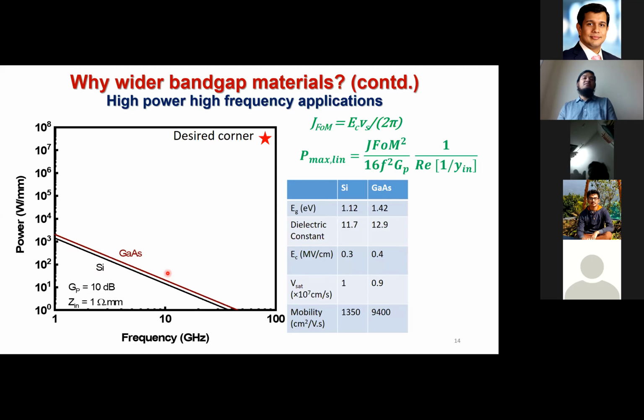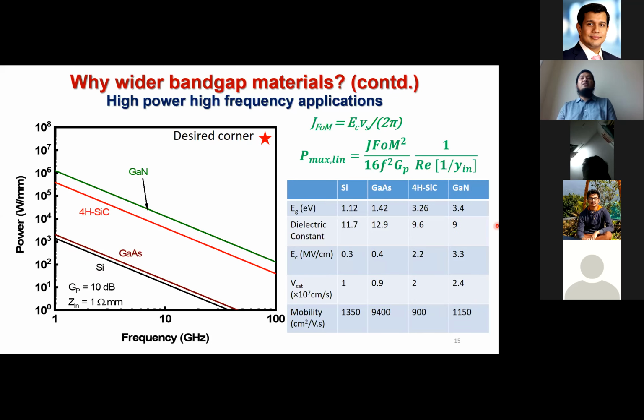Now, if you are to replace this transistor with a wider bandgap semiconductor, again, I'm talking about silicon carbide and gallium nitride, we can see that we can again get orders of magnitude improvement in how much power it can deliver in a power amplifier at a given frequency, or at a given power, how much higher frequency it can operate. Looking at this figure of merit, just from a material perspective, we are excited that if we can replace existing silicon or gallium arsenide technologies for power and high frequency application with a wider bandgap material such as gallium nitride or silicon carbide, we can enable many new applications that have never been possible before.